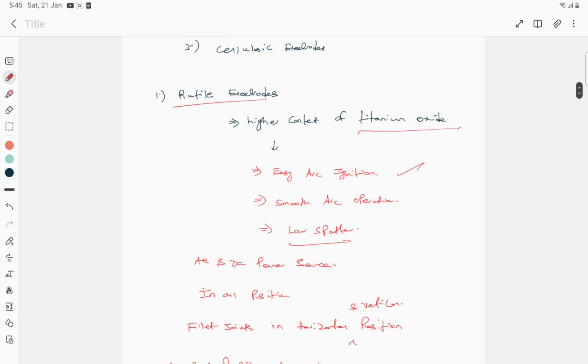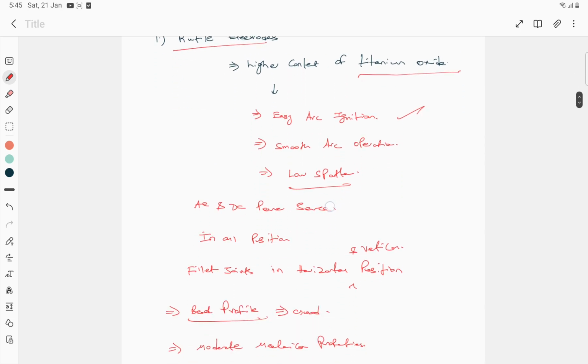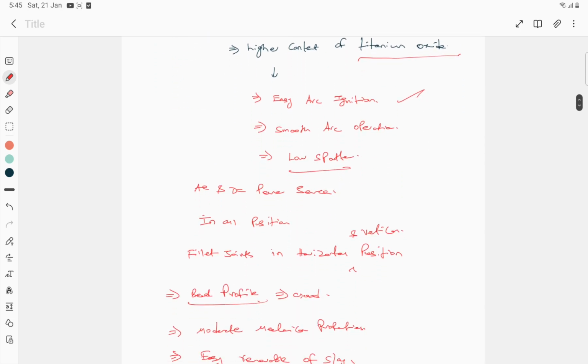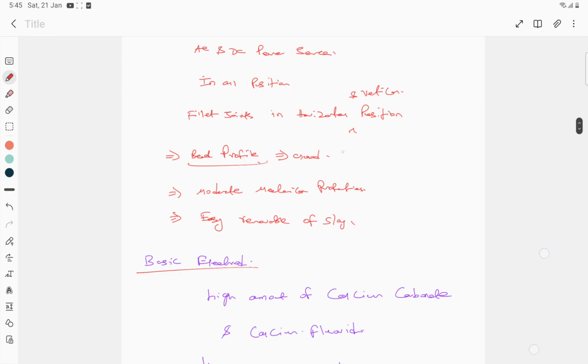Whereas in case of rutile based, it will contain a high amount of titanium oxide, and it will help us to initiate the arc easily, and then we will have a smooth arc operation, and the spatter is also very less. Okay, and the bead profile is better here. Removal of slag is easy, and we can get moderate mechanical properties. So according to our need, we can choose the type of covering on the electrode, and we can perform the welding process.